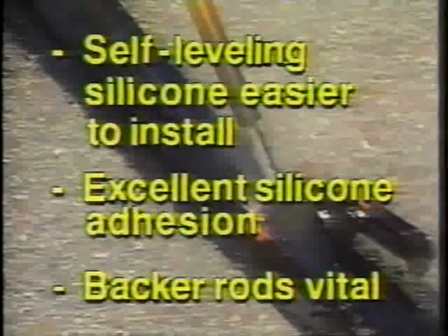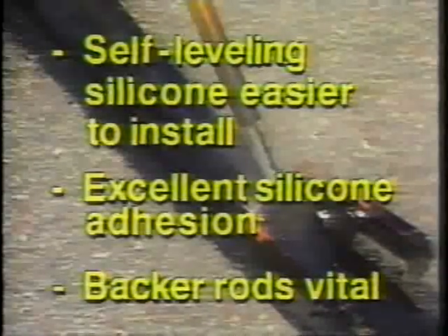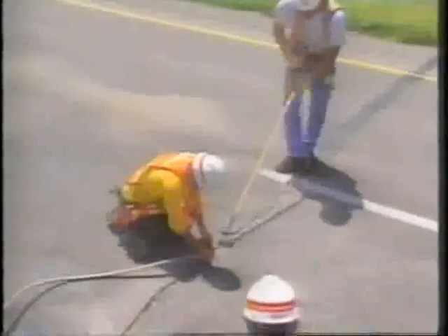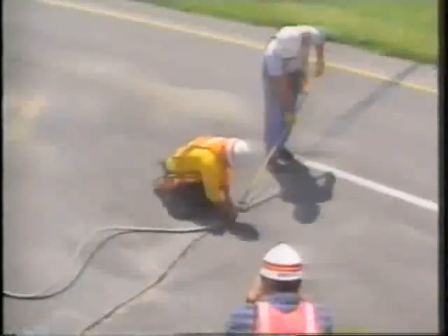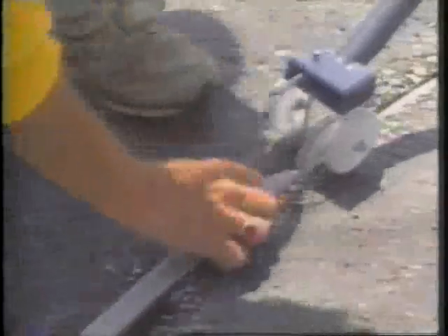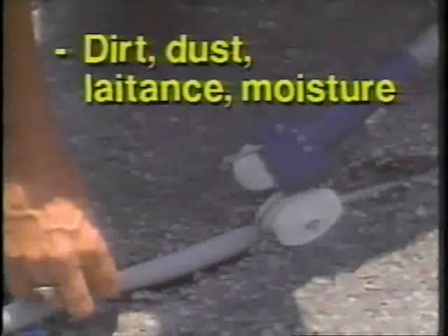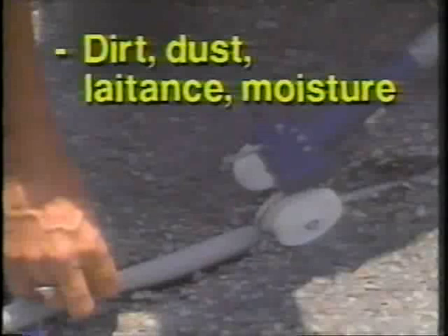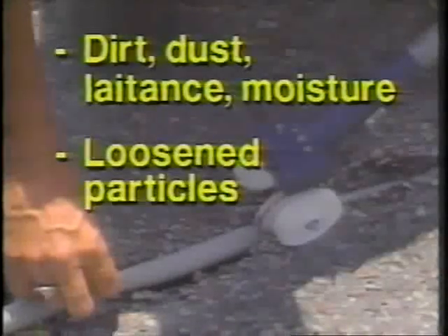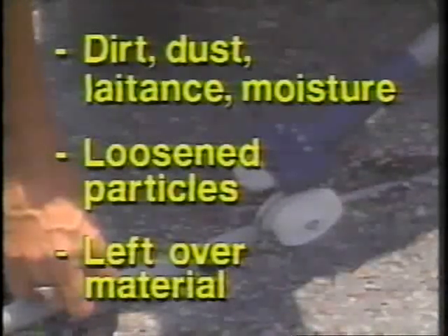Backer rods are vital. They serve the dual role of providing a bond breaker at the base of the reservoir and support for the sealant material during setting. Early results indicate that sealant construction-related failures are caused by 1. The presence of dirt, dust, old material, and moisture prior to sealing. 2. Loosened aggregate or pavement fragments not removed by cleaning operations. And 3. Leftover material, such as old asphalt sealant, remaining in a joint sealed with new silicone.